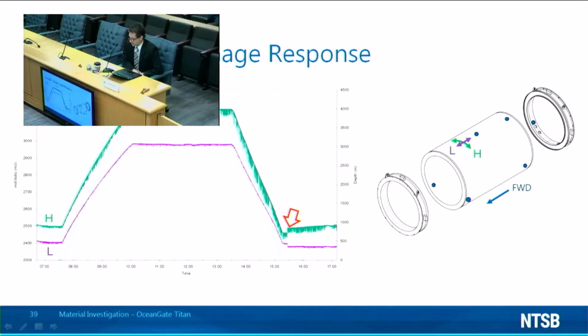Several strain gauges also responded to this event. The graph on the left shows the hoop and longitudinal strain responses during the dive for Group 4. As Titan descended, the gauge outputs increased in response to the external pressure as expected, and during the ascent, the output decreased as expected. Shortly after returning to the surface, the hoop and longitudinal gauges both showed a sudden shift in gauge output as indicated by the red arrow.